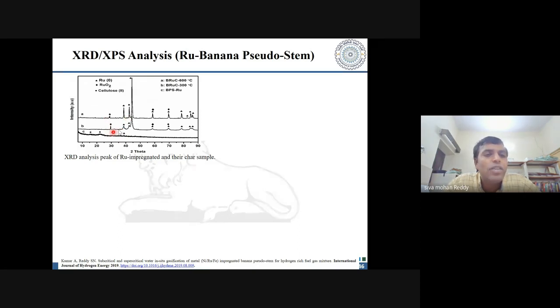But whereas if you are going to treat it at 300 degrees centigrade, we see that it forms both the oxide ones, but majorly it forms the active form of your ruthenium, which is around 44 degrees of 2 theta. At 2 theta of 44 degrees, you have an active ruthenium metal. So Ru0 means that it is in its metallic form. It doesn't have any oxidation state, that is, not +1 or +2.